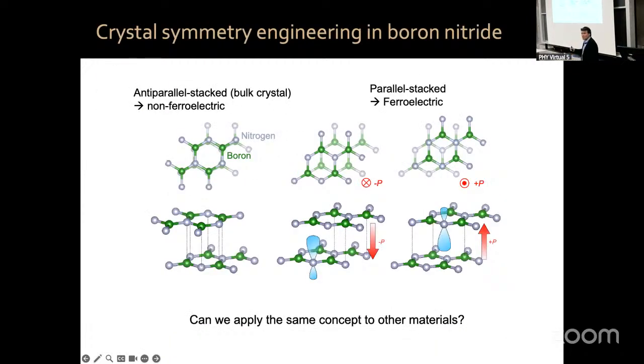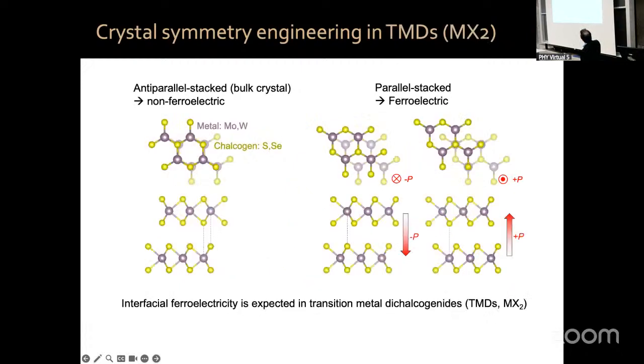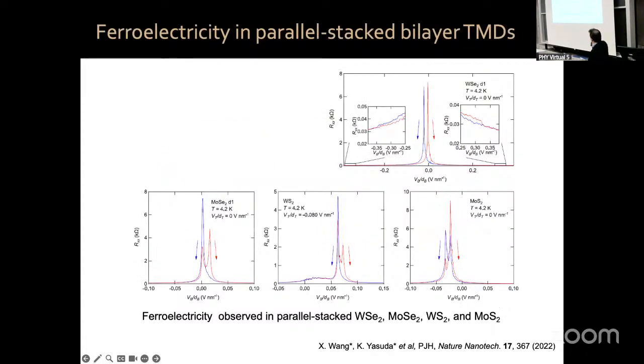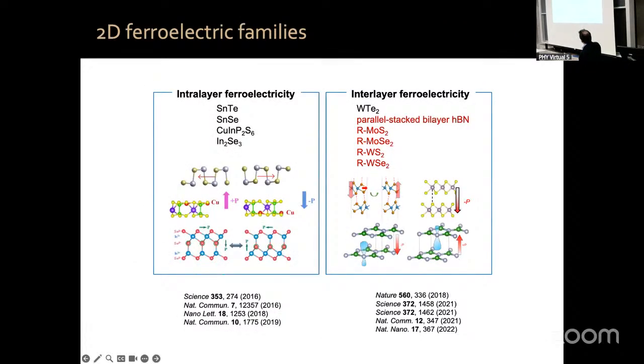All we needed to do this was this AB sublattice, the symmetries. So we asked, can we do this with other materials? Yes, in particular the transition metal dichalcogenides have the same structure. So within 6 months of the previous results, we realized ferroelectricity—these are data at 4.2 kelvin, but this works at room temperature—with all the transition metal dichalcogenides, the most famous ones, the semiconducting ones. So that means that within the span of a few months, we have essentially doubled the number of 2-dimensional ferroelectrics.